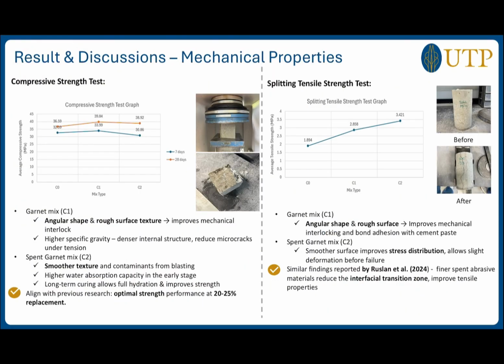Next, for mechanical properties, we have the compressive strength test and also the splitting tensile strength test. For the compressive strength test, from the graph here, we can see the garnet mix has the highest strength at 7 and 28 days. It is because of the angular shape and rough surface texture, which improve mechanical interlock.